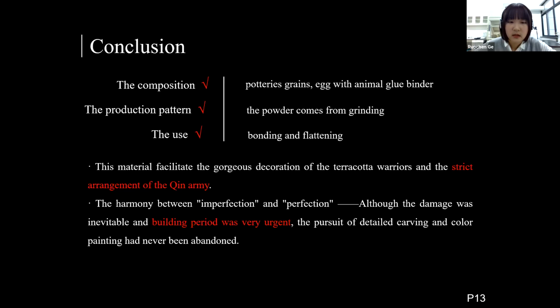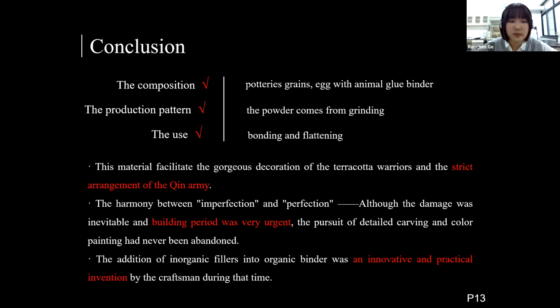produce new ones. Third, as mentioned before, this material has enough bonding strength for holding huge statues and is easy to be molded and flattened and resistant to aging and loss. This mixed use of an inorganic filler and organic binder is a crucial reason that it can be used in many ways. Adding inorganic fillers to the organic compound helps solve the problems of using organic compounds alone, including slow solidification, the poor filling ability, and difficulty to reprocess.